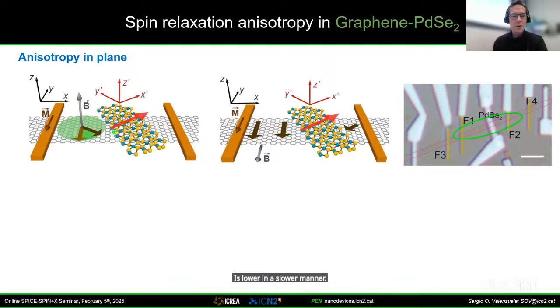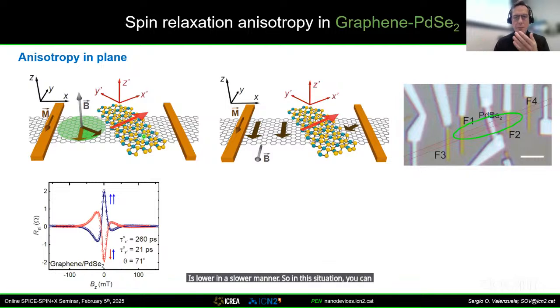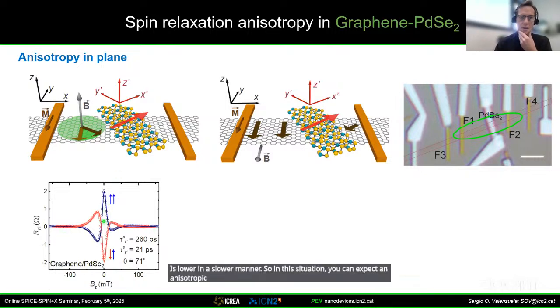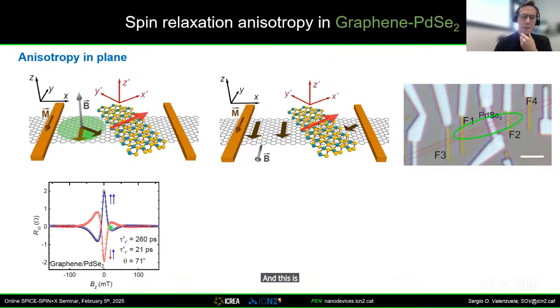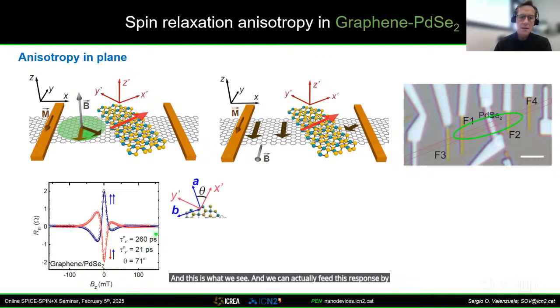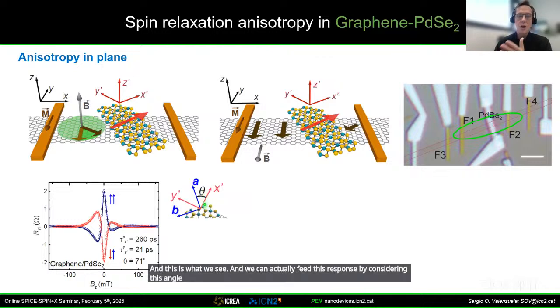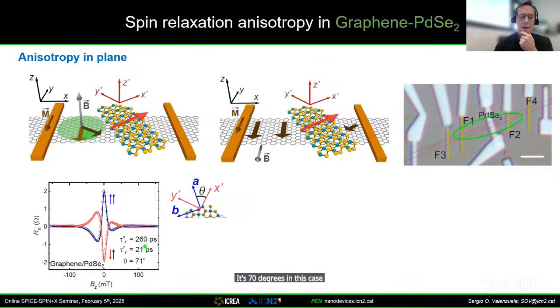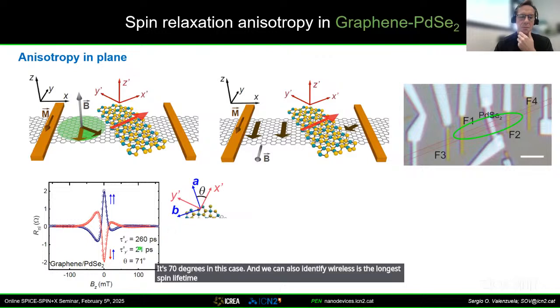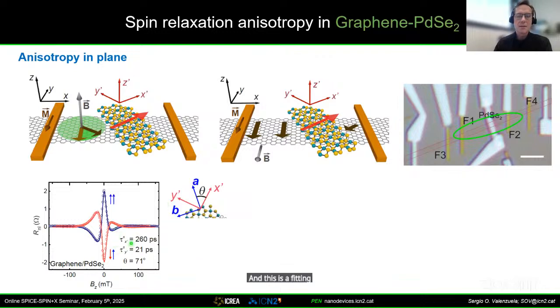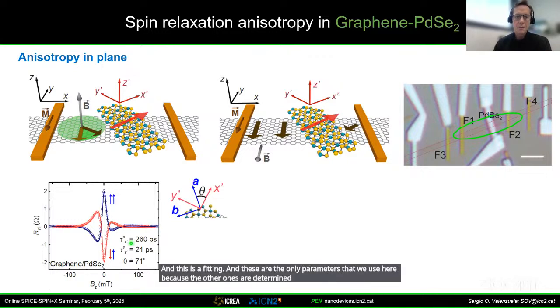So in this situation, you can expect an anisotropic response. And this is what we see. We can actually fit this response by considering this angle, which is not 0, it's 70 degrees in this case. We can also identify the longest spin lifetime along this spin orbit field in the plane and the shortest spin lifetime perpendicular to it. And this is a fitting. These are the only parameters that we use here, because the other ones are determined with the reference device.